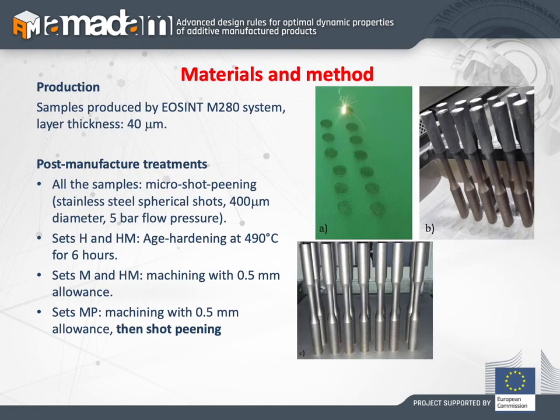Here you can see the specimens and the production system. As I told you before, we used an EOSINT M280 machine. The layer thickness is set at 40 micrometers, and here you can see the characteristics of micro shot peening. We use spherical shots with a 400 micrometer diameter and 5 bar of flow pressure. The aging treatment is at 490 degrees for 6 hours, and the allowance is 0.5 millimeter. That is the minimum allowance, because we discovered that the allowance has no effect on the fatigue results.